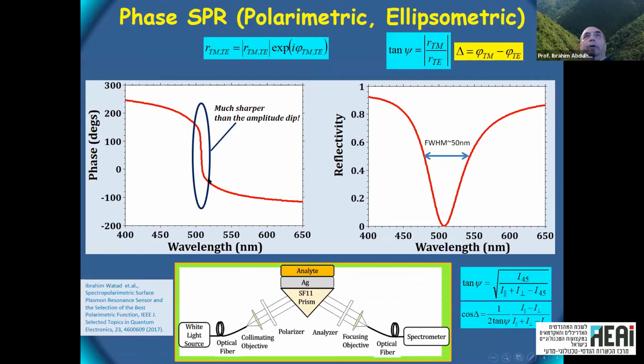So the phase one, if you look at the phase, like with any other resonance, usually there is a jump in the phase, and this jump is quite sharp, sharper than the resonance itself. So if you are able to measure the phase in some way, then you can get better detection. There are some arguments about this, because by the end, you're actually measuring intensity. So measuring intensity should be determined by the signal to noise ratio. Well, it's true, but still, because of the sharpness, you are able to get a better result.